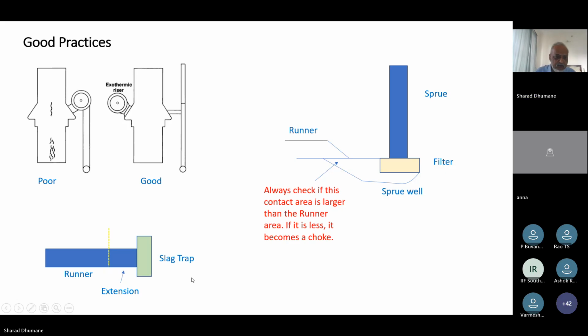Slag trap. So slag trap, this is slag. We all know that runner extension is required, but many times people don't give a runner extension. So what runner extension does is, when the initial metal flows like this, the liquid slag or the metal front, which is highly oxidized, collects air entrapment, air bubbles. So the initial metal is actually something which has liquid slag, entrapped air, and other things, maybe some eroded sand also.